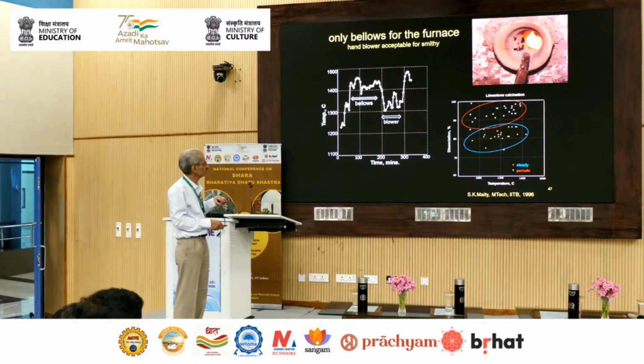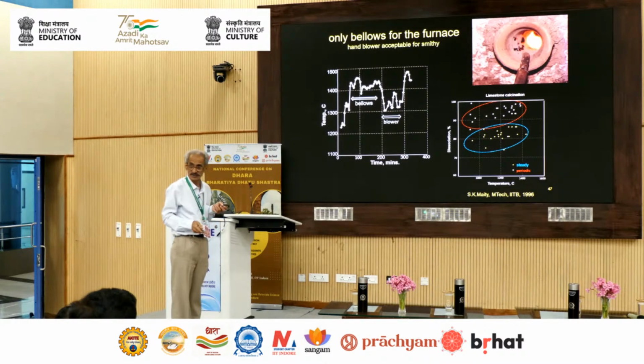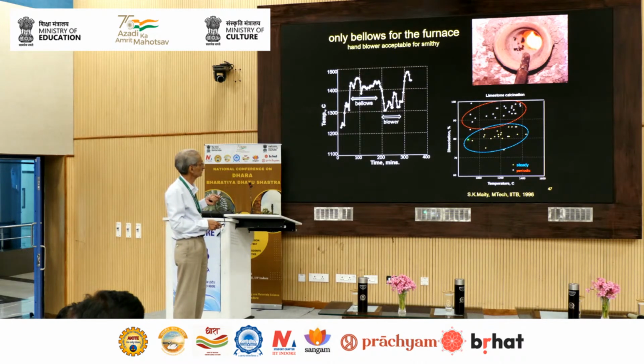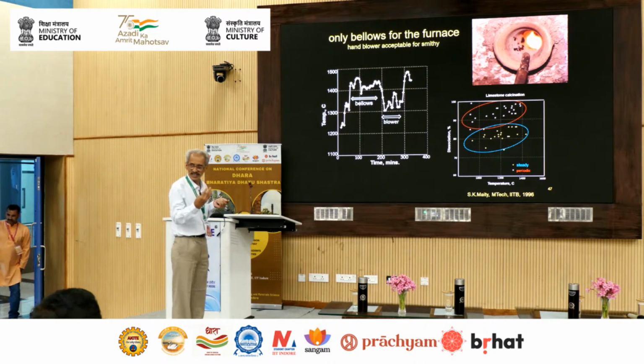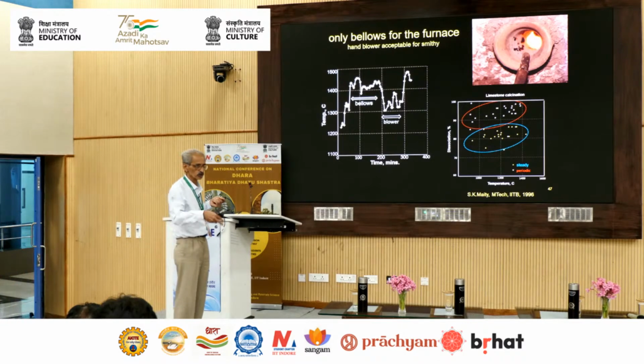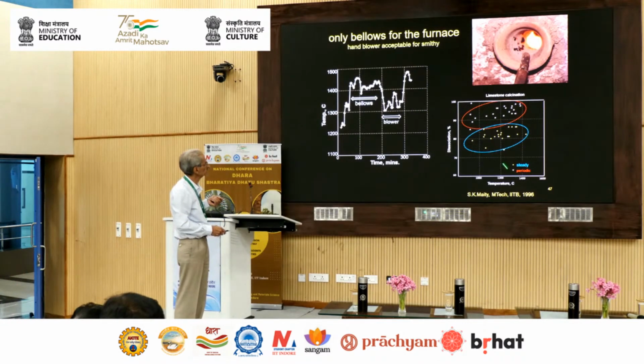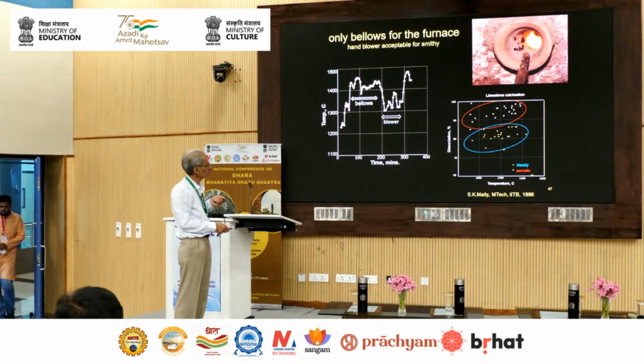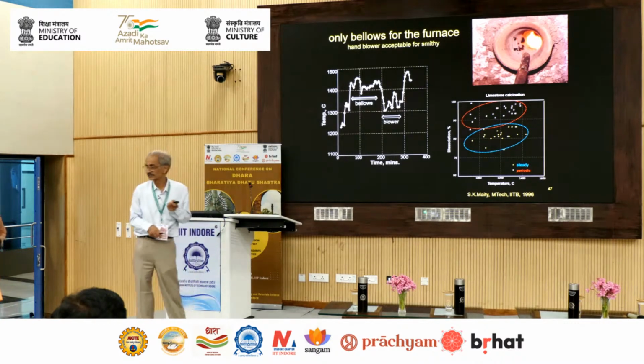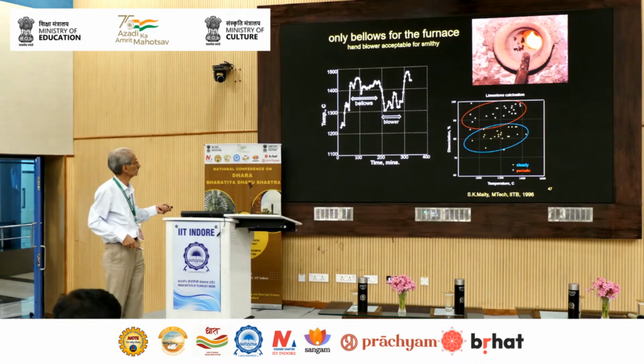So, and then I had an MTech student and we wanted to try, he was doing some limestone calcination in a packed bed, of course not in the bhatti, but a calcination. So that also has a blow of air burning the coke breeze that is mixed with limestone. This is with steady operation, percent dissociation, and this is of course at various temperatures. And you see the band is here. And we shifted, for the same amount of air blown, to periodic operation, the band went up by almost 10% dissociation, showing that this really improves the process.